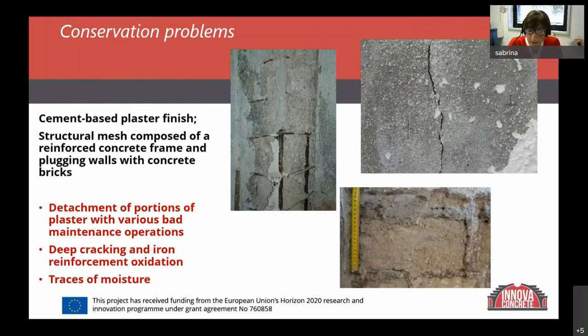As concerning the conservation state, the monument showed major problems of rising humidity, certainly generated by the location of the pillars on the ground, with the consequent detachment of portions of the materials and internal bars of armor very oxidized. At the direct site, it seemed therefore even more subjected to degradation. Moreover, on the load-bearing pillars, some previous restoration works, consisting in application of different cement mortars, showed already partial detachment, with micro and macro cracks, particularly concentrated near the reinforcement irons.